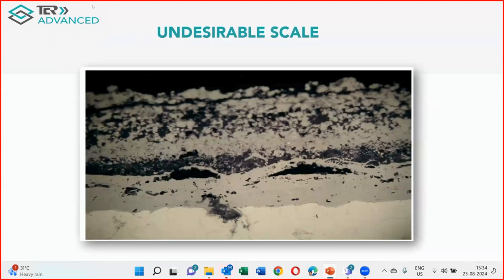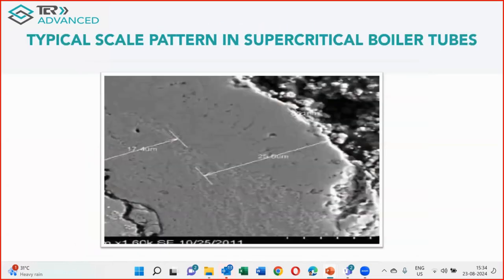Now, this is a typical photograph of a scale, which shows a very undesirable scale, where you can see there are gaps, porosities, and cracks in the layer. Instead of protecting, when there are gaps, it hampers the heat transfer, because you all know that as the gap increases, it gets worse. So this is something which we need to look at very, very carefully. A very intact layer, the layer shown at the bottom, has to be formed in the boiler. Now, the theory in the subcritical boiler is different, and the theory in the supercritical boiler is different.